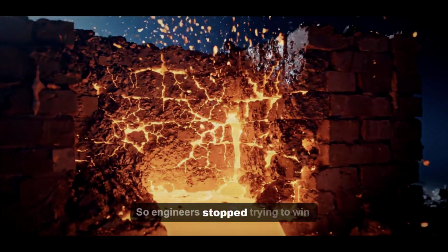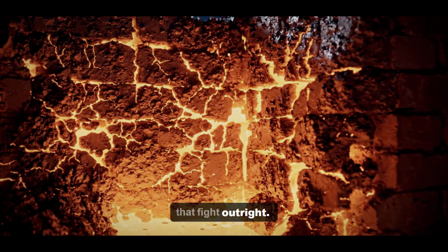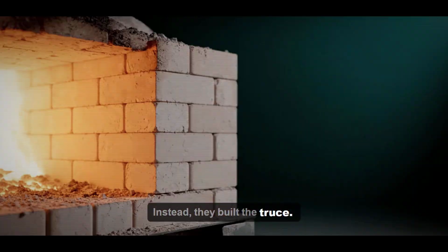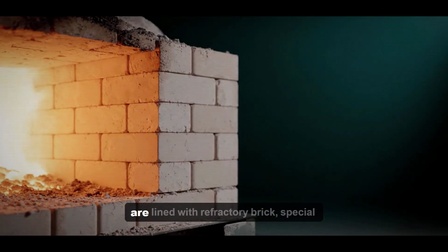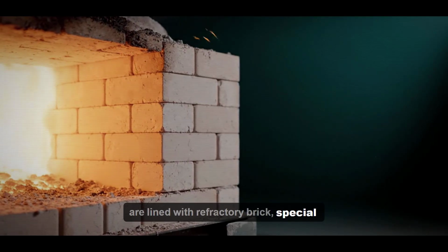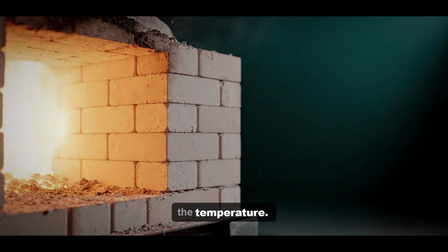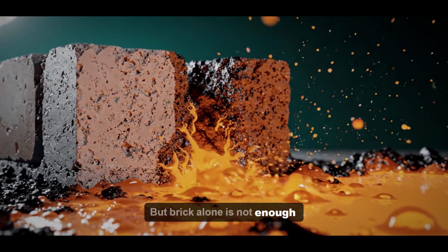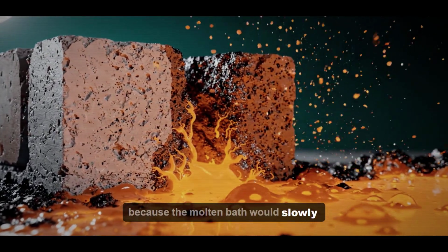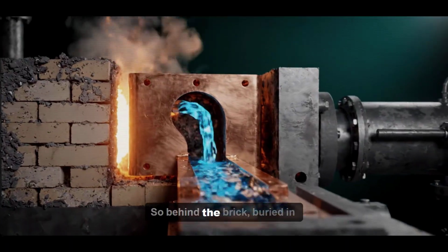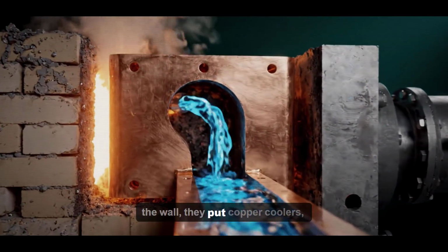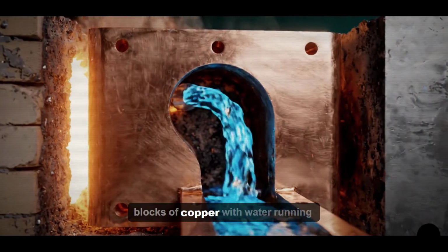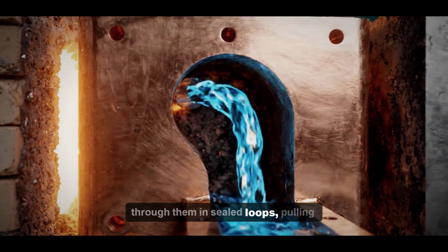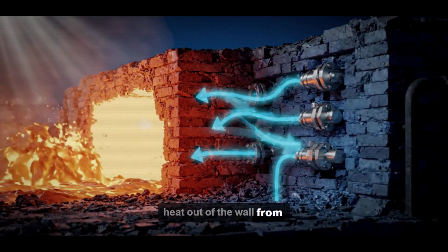So engineers stopped trying to win that fight outright. Instead, they built the Truce. The walls of a modern smelter are lined with refractory brick, special heat-resistant material that can take the temperature. But brick alone is not enough because the molten bath would still slowly eat through it. So behind the brick, buried in the wall, they put copper coolers, blocks of copper with water running through them in sealed loops, pulling heat out of the wall from behind.